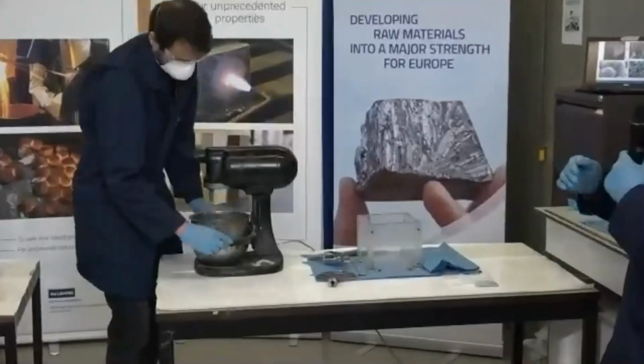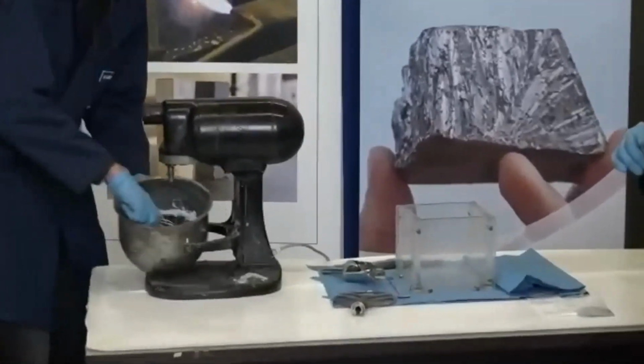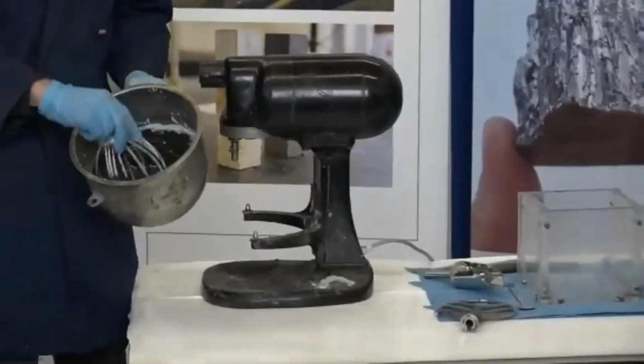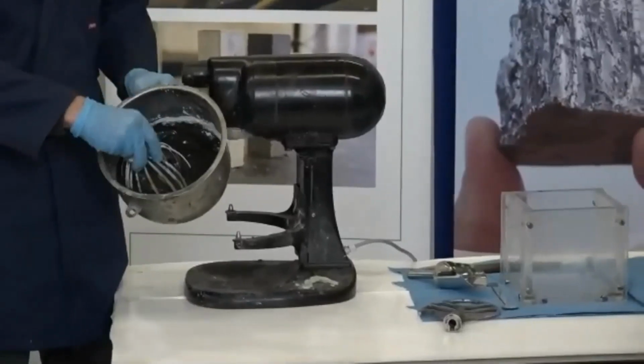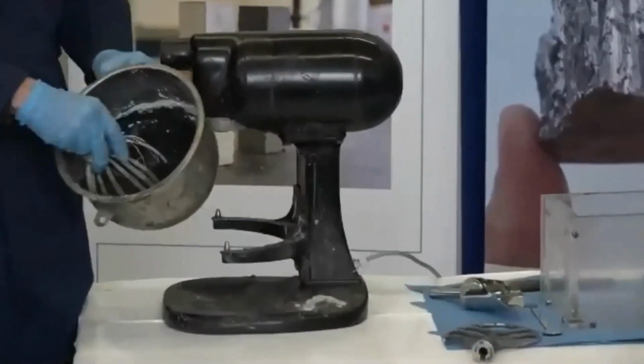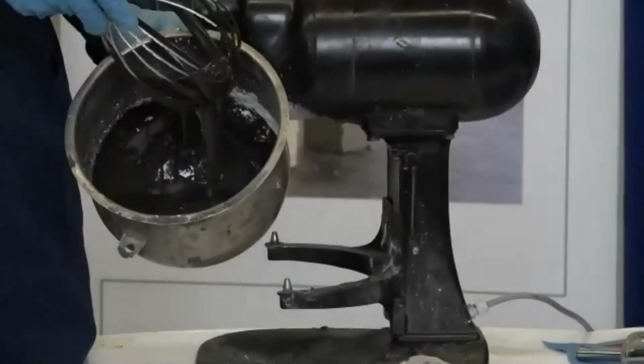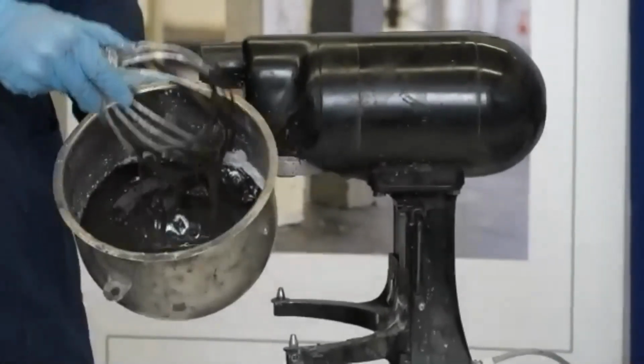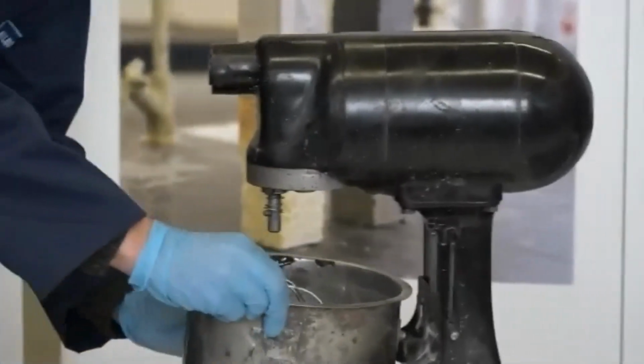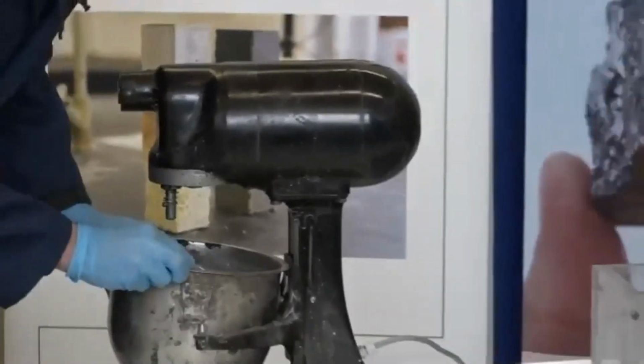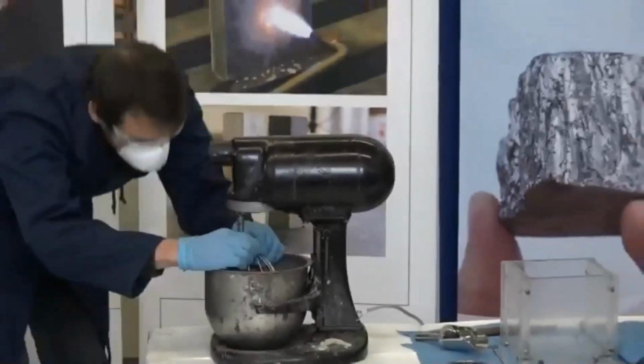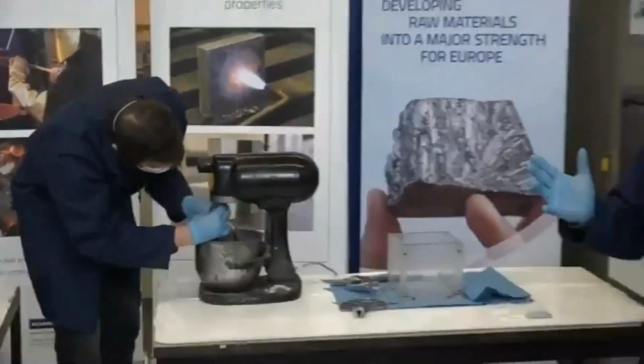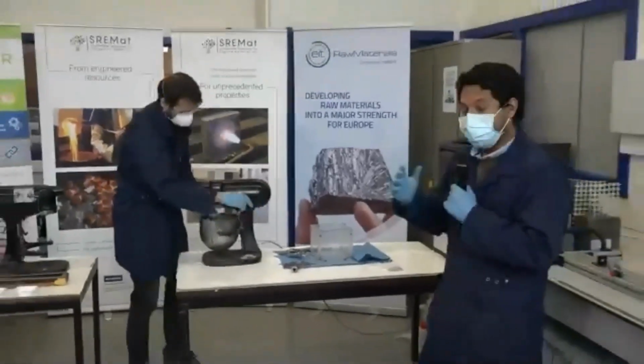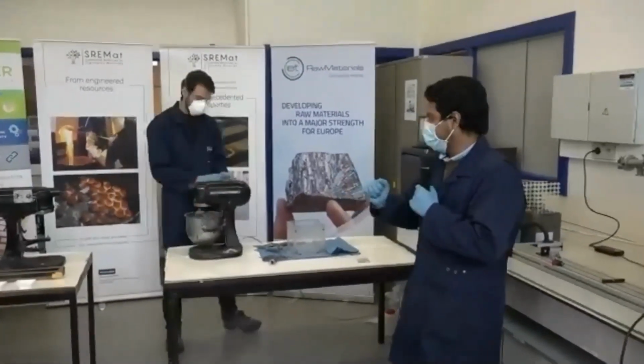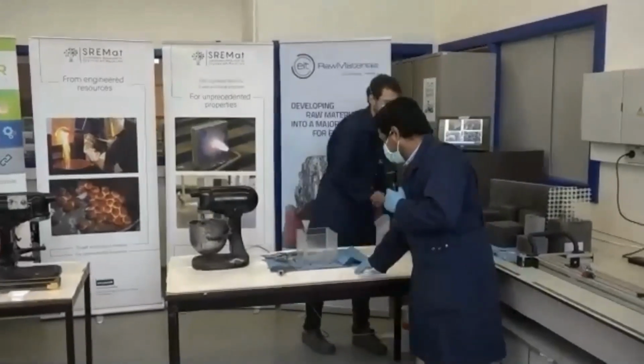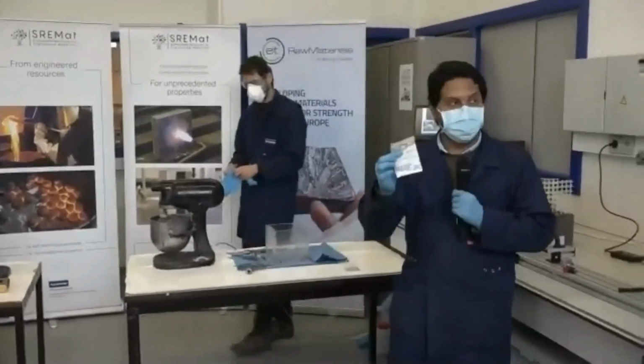So right now, Tobias is going to show you how this paste looks like. It's a little bit different to what you saw at the beginning with the other mixture, but this is what we want. We want a viscous mixture, still, which is very castable, which is important for the next step of the process. So now we have the initial precursor, which is going to be, after curing, the inorganic polymer. The next thing that we will do is to introduce this little powder over here.